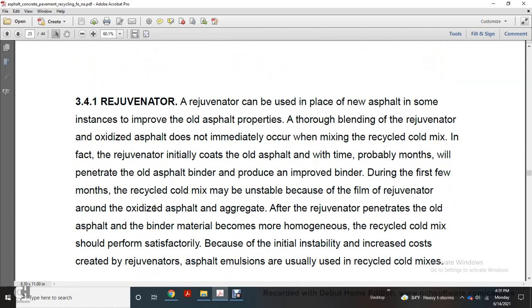Rejuvenator. Rejuvenator can be used with the new asphalt to soften the old asphalt properly through blending of the rejuvenator with the oxidized asphalt. This does not immediately occur with the mixing of the recycled cold mix. In fact, the rejuvenator initially coats the old asphalt, and over a period of months it penetrates the old asphalt binder and improves the binder during the first few months of the recycled cold mix.